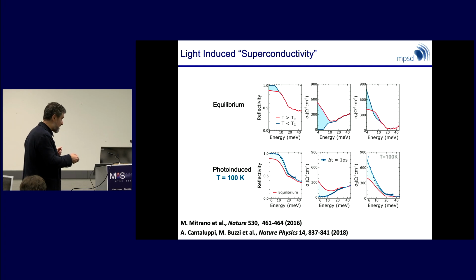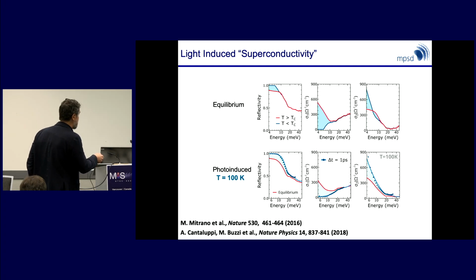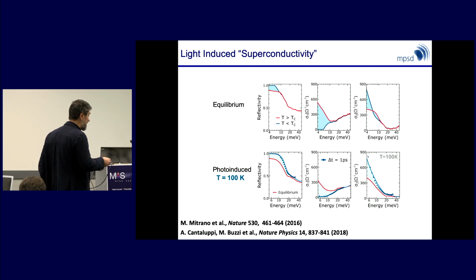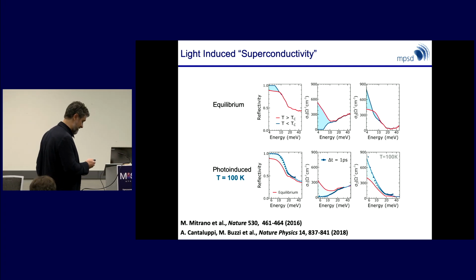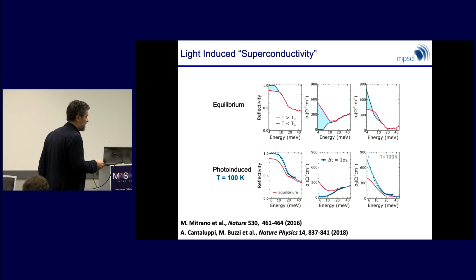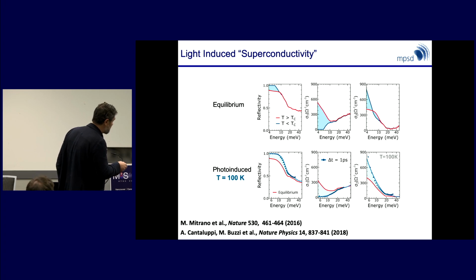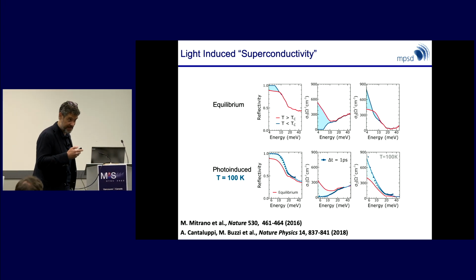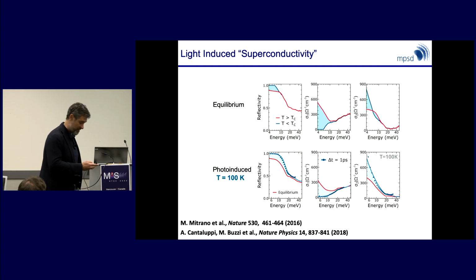This is the results. This is not Matteo's data, but I'm purporting it to be. Basically, this is the equilibrium optical properties when you cool the material below 20 Kelvin. And this is the transient optical properties extracted by measuring the reflection of the Terahertz pulse at 1 picosecond pump probe time delay. And what you observe is a very suggestive similarity with the equilibrium properties of the 0 temperature or low Tc material. I will point out that within the limits of this reconstruction, what we observe is a light-induced divergent sigma 2, which has the same size as the one that you observe in equilibrium, suggesting that you are promoting a superfluid that has the same density as the one that you would observe at 0 temperature.